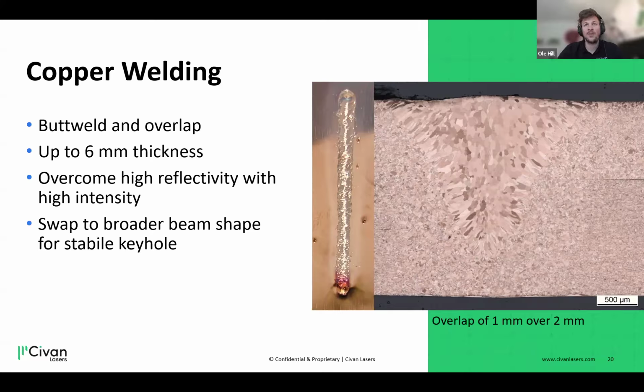You do that because you typically have better beam quality and also lower cost per kilowatt in the infrared regime. But synchronizing two lasers is, as you can imagine, not that simple. We have a similar idea when welding copper. We first use a very concentrated beam shape, which has really high intensity on a single spot. And after the first millimeter of welding, we switch to a different beam shape.